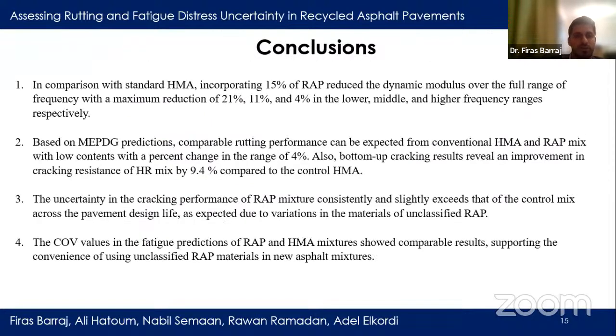And finally, the conclusion here, we can start with conclusion number 1. In comparison with standard HMA, incorporating 15% of RAP reduced the dynamic modulus over the full range of frequency, with a maximum reduction of 21%, 11%, and 4% in the lower, middle, and higher frequency ranges, respectively.